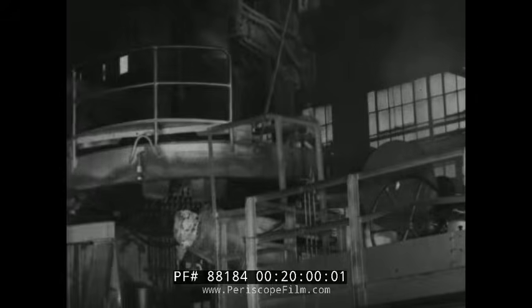When the furnace is fully charged, the top swings back into place, the electrodes are lowered into position, the current is turned on, and the melting begins. This non-ferrous electric furnace will melt 40,000 pounds of metal at one heat. This 20-ton open hearth melting furnace is fired with natural gas.